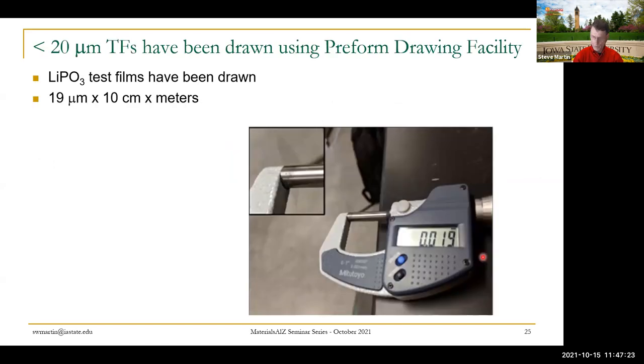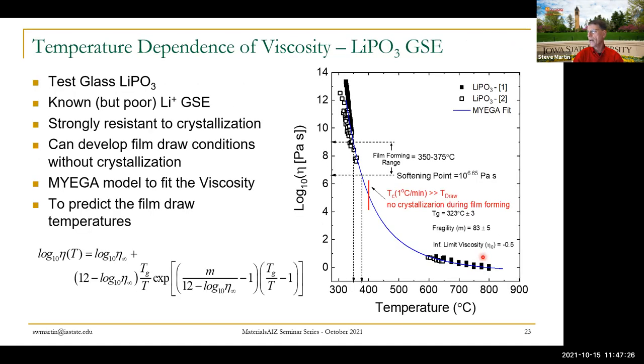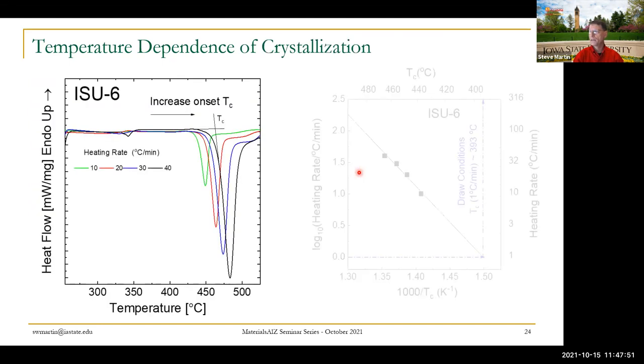And then, whoops, sorry, I have to go backwards, apologize for that. Then we can take that point and put it onto our viscosity curve. And that gives us a qualifier. We knew LiPO3 was a strong glass former, but it means we can say that's why we can draw the film without crystallizing, because our crystallization temperature at those drawing conditions is above our draw temperature. And that's what we're doing with all our other glasses.